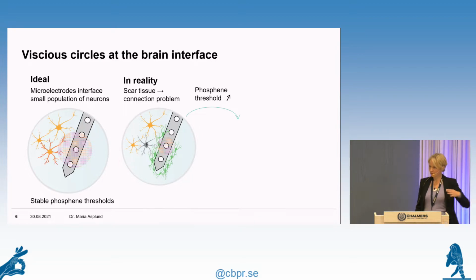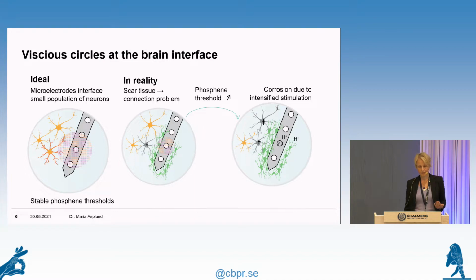We will see phosphenes going up. The threshold to inject phosphene will go up, so we will need to use more and more current, which puts our small electrodes at risk of corrosion. So most likely we will not only damage the device, but also generate electroactive species like reactive oxygen species, or change the pH. So we will have even more inflammation and even higher thresholds. So this is usually what happens.